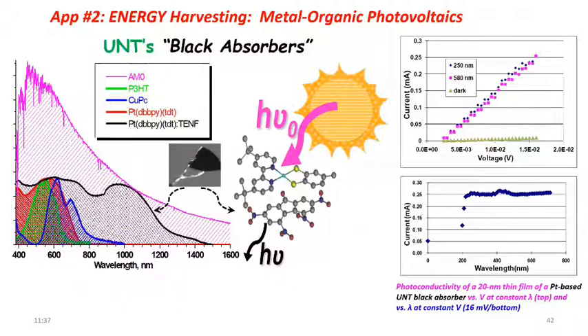The problem is that normal organic semiconductors used in the technology, like this polymer here called poly-3-hexylthiophene, P3HT, overlap pretty well with the peak of the solar radiation, but as you can see here, there is a gap in the shorter wavelength and a huge gap in the visible beyond the green region, and nothing in the near IR. This copper phthalocyanine, another well-known material, is more like a charge transporter in electronic devices. It does better at longer wavelengths, so it covers the gap in the red, but at the expense of the peak. So there's a hole here in the green and blue region, and it picks up in the UV.